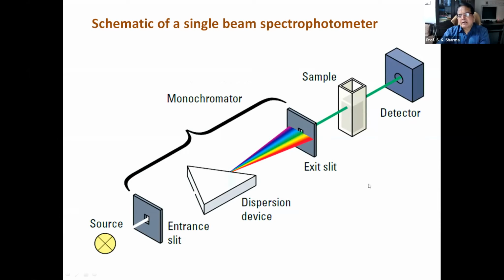That once we have a solvent there to record the baseline or to record the zero spectrum, then you have to replace it with the sample again. You have to record two types of spectrum, first with the blank sample and another with the real sample, and then you have to subtract this blank sample from the real sample, and then you get the result of those particles which are there in the sample.